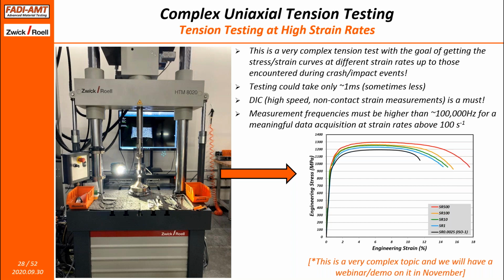One of them is the fact that when you go faster, obviously you have a shorter amount of time to measure or collect data. And when we are talking about 100 to 1,000 strains per second, you have about 1 millisecond, sometimes less, sometimes more at those speeds. And even though we have data acquisition systems that can capture data at that rate, which is for load, there isn't an easy way to capture the displacement or the strain at that kind of a rate or that kind of frequency. And of course, the second problem is you can't use any form of contact extensometry here.